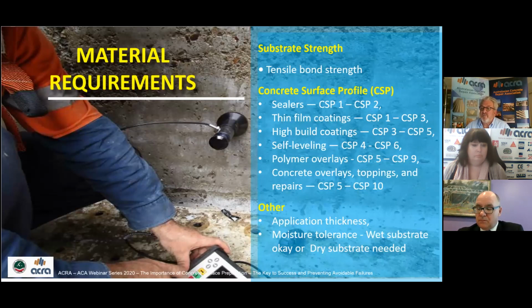Substrate strength, we've got the tensile bond strength. Generally, that's tested prior to and or after following surface preparation, where we actually do an adhesion test on the substrate strength. Most coatings and repair materials require a minimum substrate strength of 1 MPa. Then we've got the profiles that we require. We'll get onto the CSPs further on in the presentation, but there's different profiles there for different materials and toppings. And the other one is the application thickness. Moisture tolerance product, wet substrate, is it okay? Or do we need a dry substrate?